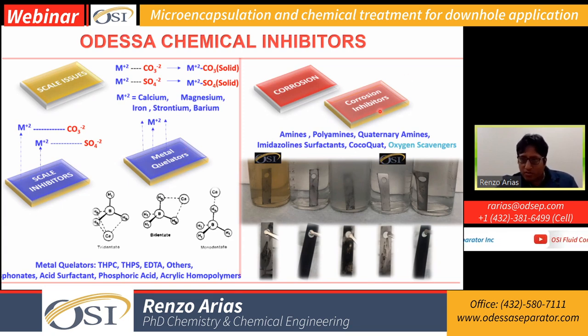In the case of corrosion inhibitors, our cocktail of chemicals is based on amines, polyamines, quaternary amines, imidazolines, surfactants, and CocoQuat, and we are currently working on some oxygen studies. Remember, one of the major factors that increases corrosion downhole is the presence of oxygen as well. So we're working on microencapsulating some oxygen scavengers to provide better performance for these corrosion inhibitors.